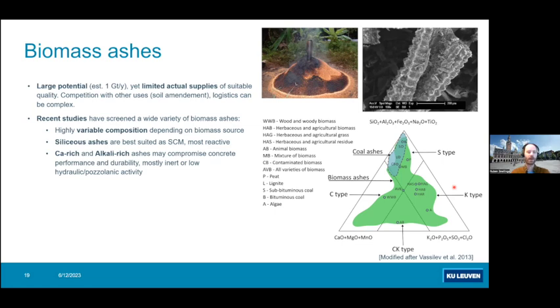Those materials that produce siliceous ashes are best suitable and they are most reactive. So we're thinking here about herbaceous materials. Rice husk ash is a very well-known example of this. While on the other hand, calcium-rich and alkali-rich materials or ashes may compromise performance and durability.